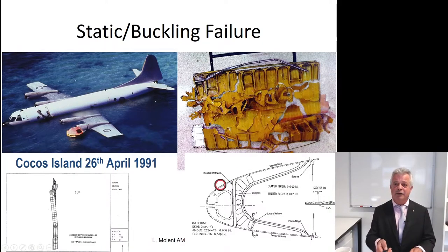And it just so happened that this particular aerofoil at that condition experienced a transonic or supersonic shockwave, and that increased the loads, okay? But that wasn't sufficient to explain the failure. After many, many years and much ridicule from our good friends, the manufacturer, what we determined was that as the air loads were applied to this rib or the leading edge, so imagine that it's being bent upwards. The rib itself, if you look at it on a side view, buckled. And as soon as the rib buckled, there goes its load-bearing properties, and that's why it failed.